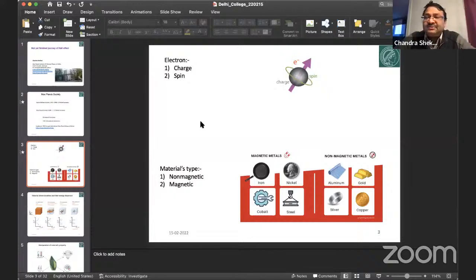So this one is non-magnetic, but there is a spin charge density wave, a charge density wave at 95 Kelvin. I think there is chiral charge order. That charge density band is due to vanadium, because vanadium is sitting on this Kagome lattice. So there is no direct evidence of TRS breaking yet.